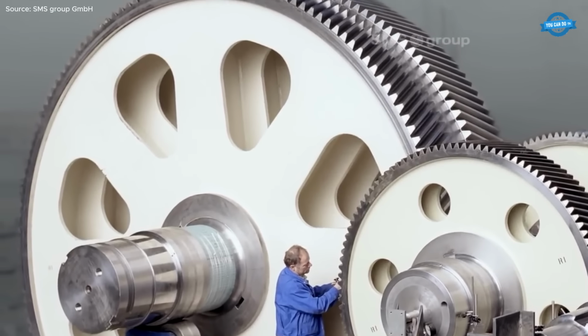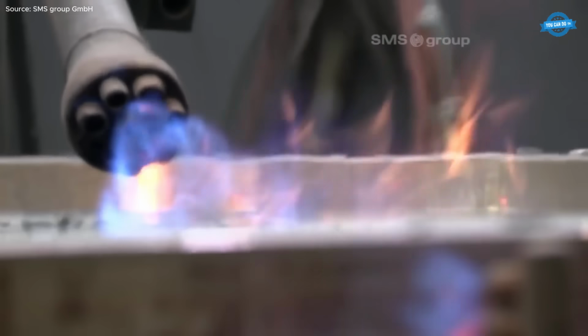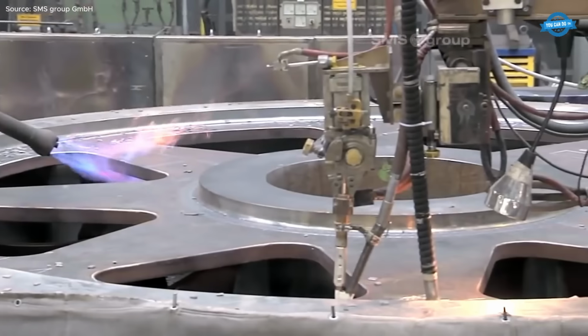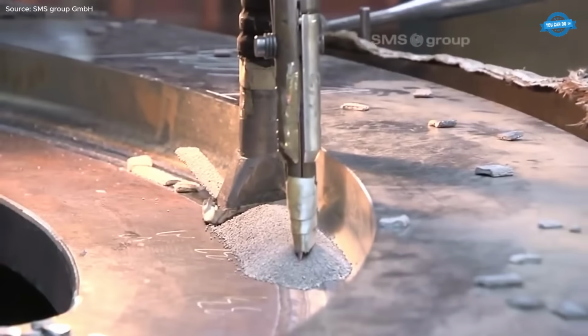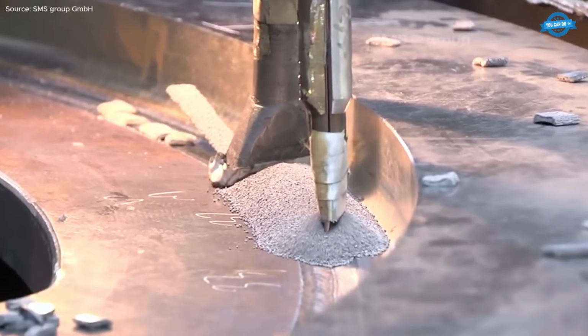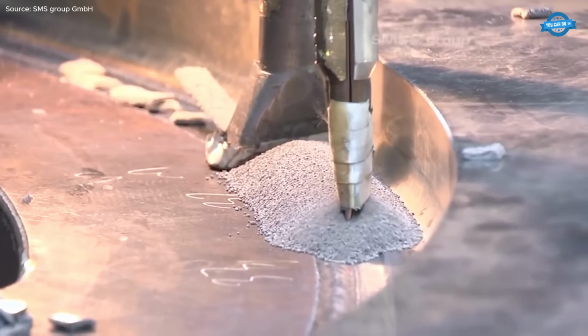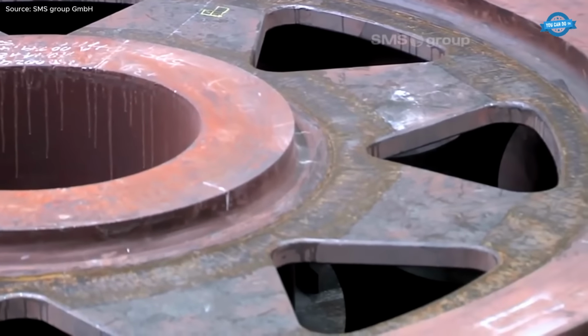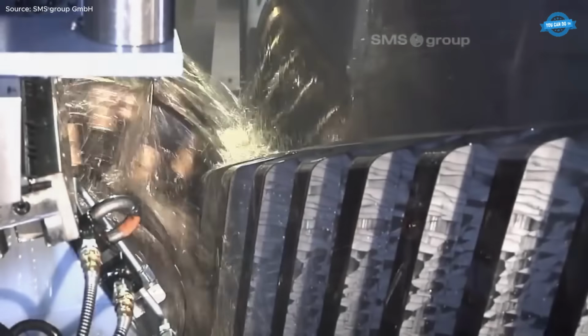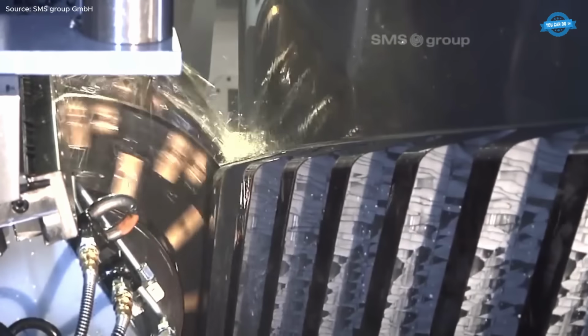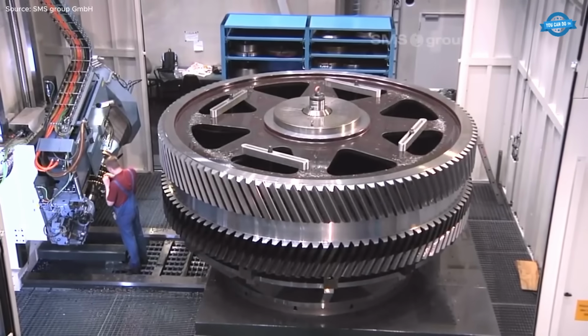For high-load applications, such as hot rolling mills, double helical gears weighing up to 45 metric tons and measuring 4.5 meters in diameter are case-hardened to achieve a wear-resistant surface with a tough core. Ultrasonic testing follows heat treatment to verify material integrity, particularly in critical tooth root zones.